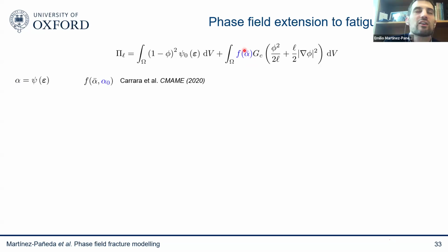So this fatigue degradation function will evolve with accumulated load. As you increase your load, as you accumulate cyclic loading, you will increase that number, and therefore you will degrade this fracture energy. And that basically means that you need to come up with, well, what drives this alpha parameter? What is the variable that is accumulating? Well, that's simple. We keep it energetic. It's driven by the strain energy density. And also you need an extra parameter.